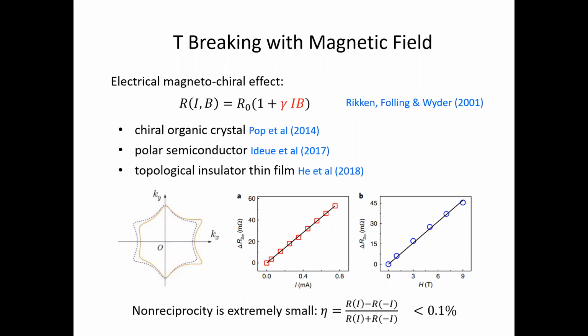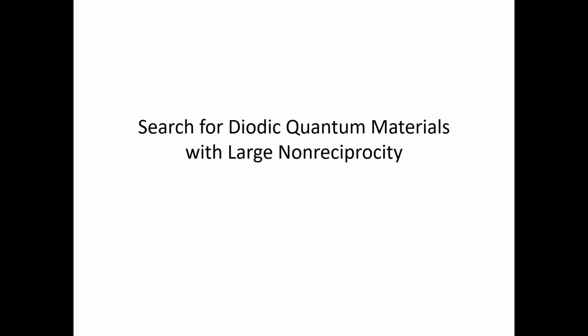So if you look at what's shown here, the dashed line is the constant energy contour of the Fermi surface at zero magnetic field. It's symmetric around k equals zero. But in the presence of an applied magnetic field, it's slightly distorted, so it's now asymmetric. However, the magnetic field energy associated with the spins, the Zeeman energy, is tiny compared to the typical kinetic energy of electrons in this material. And therefore, unsurprisingly, this non-reciprocal electrical transport is a very tiny effect. So in this talk, I'm going to focus on some recent developments where we have found, as a community, diodic materials with very large non-reciprocal effect.